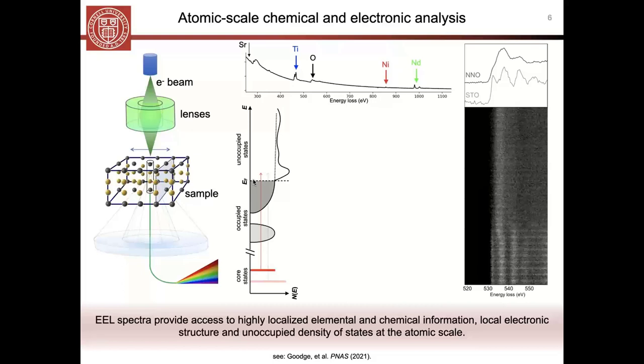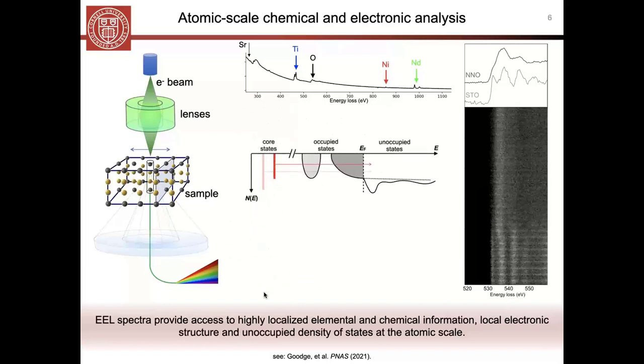What happens in the EELS process is that as the electron from the beam interacts with the electrons in our sample, we excite some of those core state electrons up into the unoccupied states. There's some characteristic energy associated with that transition. If we turn this schematic on its side so it looks like an EELS spectrum, you can see that by looking at the intensity distribution of how these excitations occur, what we're basically mapping here is an EELS edge. This is the zero order understanding of what the shape of an EELS edge tells you about the unoccupied states in the material you're interested in.